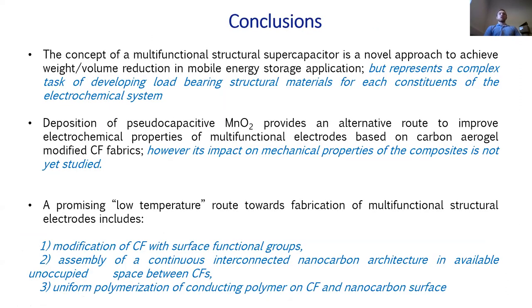To conclude with, the concept of structural supercapacitor is quite interesting from the perspective of application in mobile energy storage systems, where we can achieve a weight reduction in alternative route to conventional systems. However, it is quite a complex task, which requires a separate research project for each constituent or element of our supercapacitor. The manganese oxide decoration route enables us to improve the chemical performance of our structural electrode based on the carbon aerogel carbon fibers, which is currently considered being the state of the art. However, its impact on mechanical properties is still not yet studied.